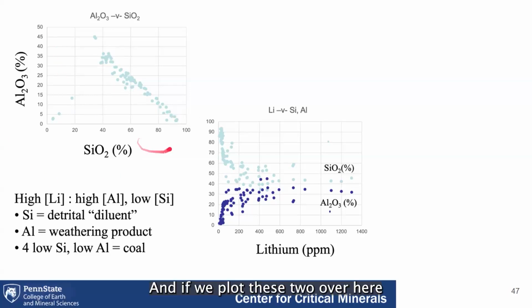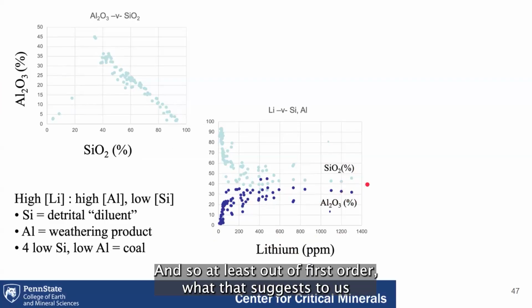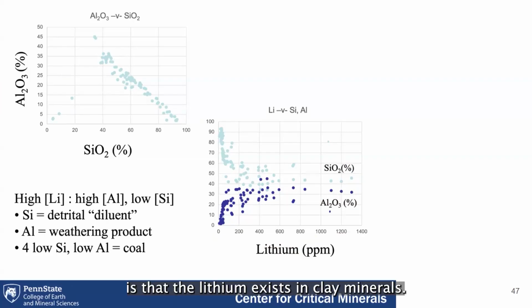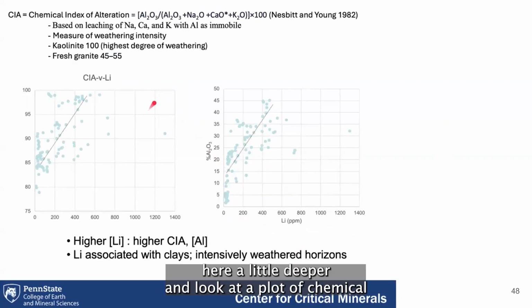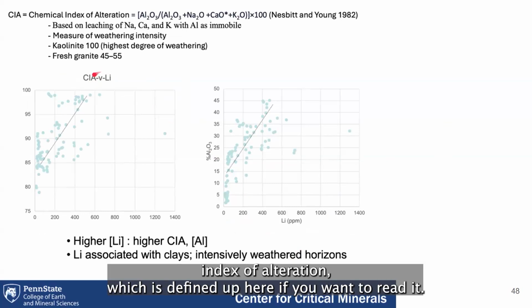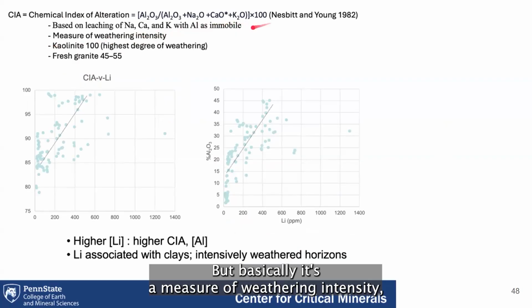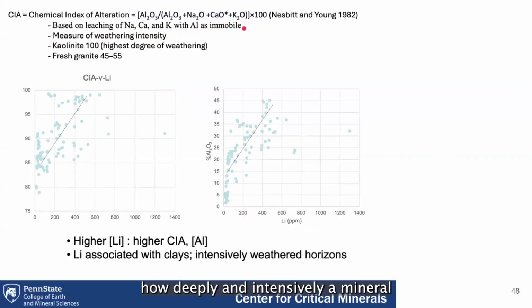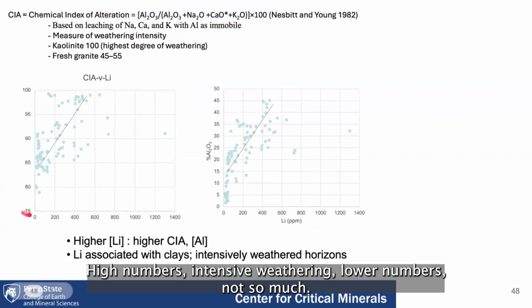And if we plot these two over here versus lithium, what you can see is that all the high lithium values occur within the lowest silica and highest alumina-bearing samples. And so at least at a first order, what that suggests to us is that the lithium exists in clay minerals. Now, if we dig in here a little deeper and look at a plot of chemical index of alteration, which is defined up here if you want to read it, but basically it's a measure of weathering intensity, how deeply and intensively a mineral has been weathered in a soil profile. High numbers, intensive weathering, lower numbers, not so much.